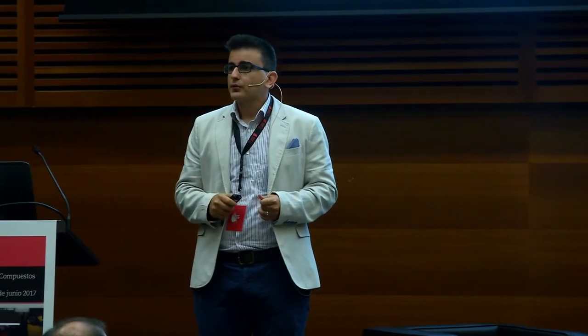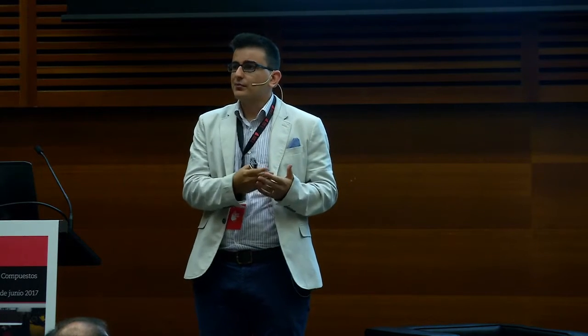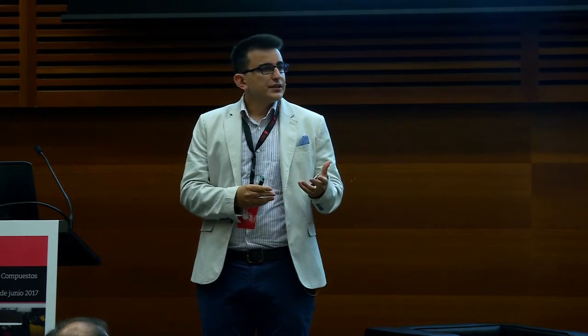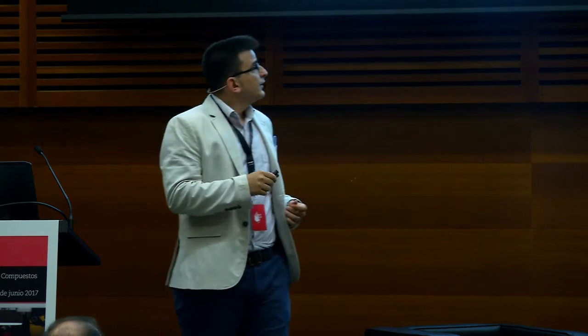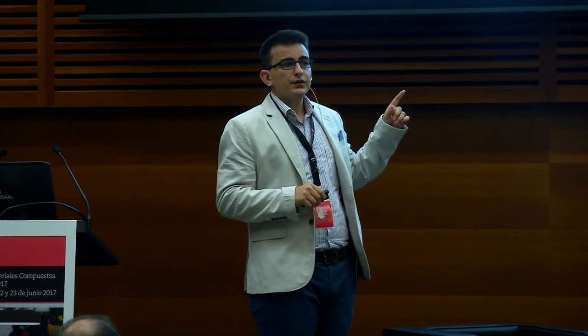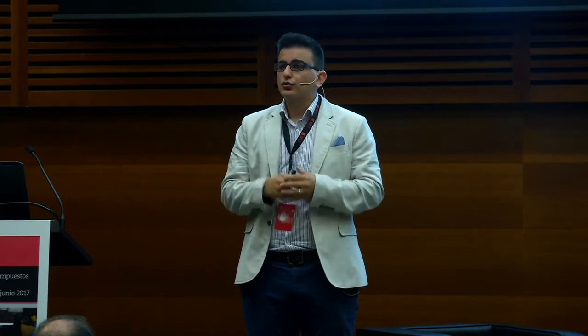So this is the stress distribution using the uniform fiber volume content. This is the transverse normal stress, and on the right hand side we have the transverse shear stresses. It's obvious that we have tensile stress in the center because curing takes place at a later stage but in a faster manner. For the maximum transverse shear stress, we have it in between the center and the outer surface, and this is again due to the non-uniform curing of this relatively thick profile.